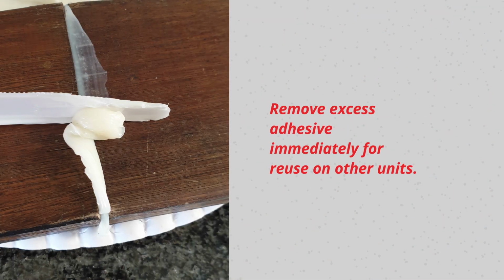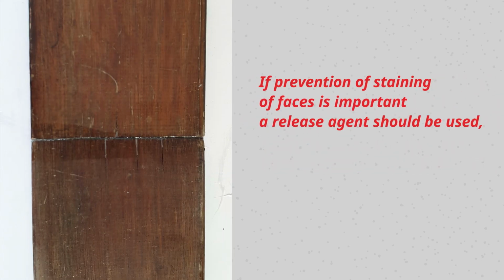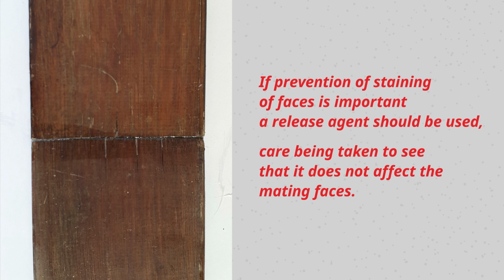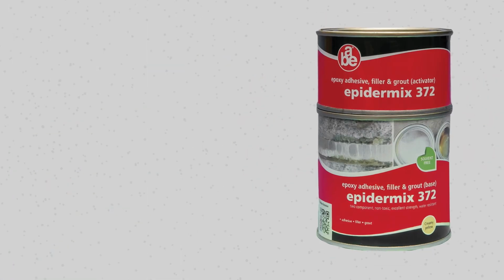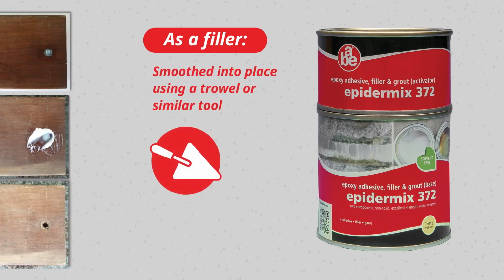Remove excess adhesive immediately for reuse on other units. If prevention of staining of faces is important, a release agent should be used, and care being taken to see that it does not affect the mating faces. Epidermix 372 as a filler should be smoothed into place using a trowel or similar tool.